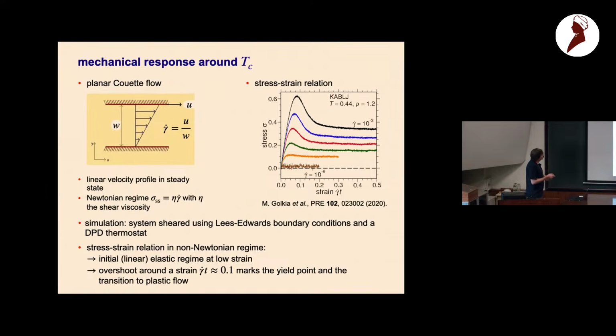This is a typical result. This is the stress-strain relation for the Kob-Andersen mixture at density 1.2. Here, the lowest shear rate at this temperature reflects the Newtonian response. Here we are in the linear response regime. As we get to the nonlinear response, we have the emergence of this overshoot, which occurs around a strain of 0.1, and it marks the transition to plastic flow.